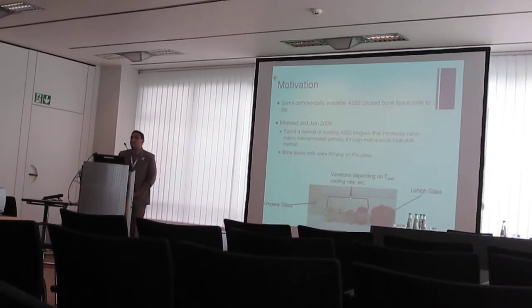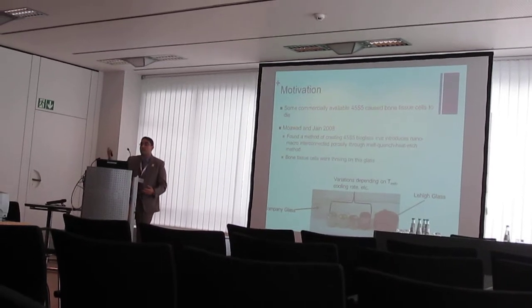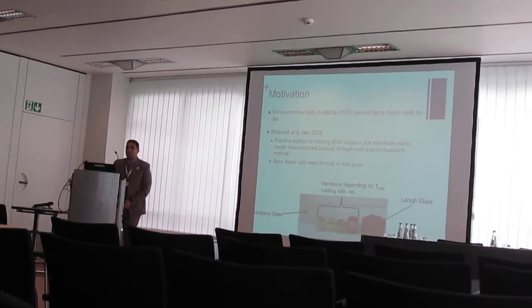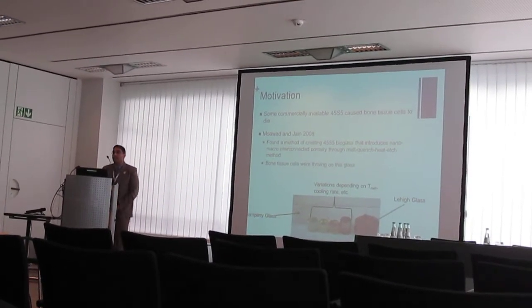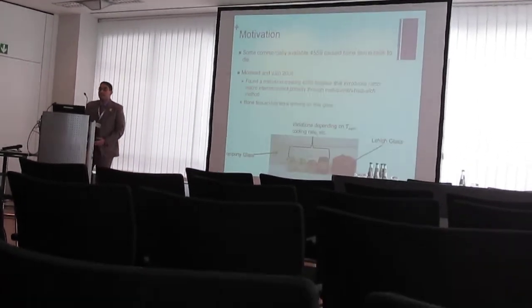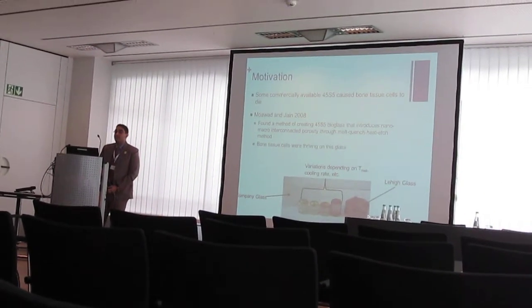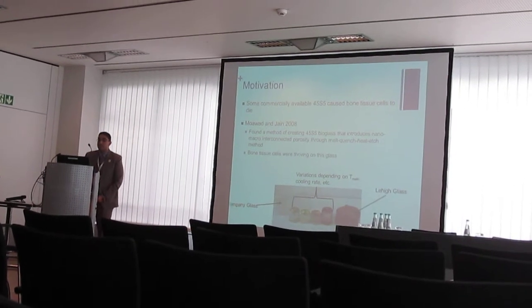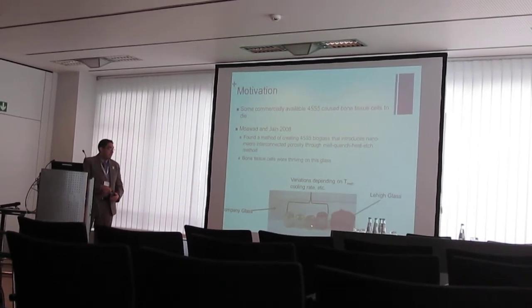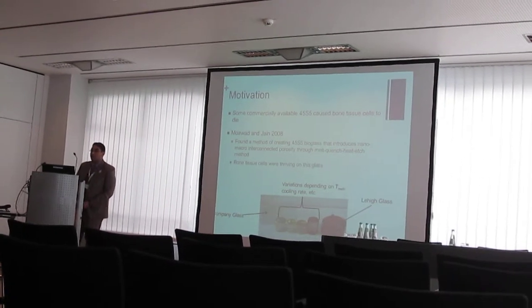We were very interested in seeing what caused this, and we tried to vary the different parameters in the melt quench technique. We determined that if we vary the melting temperature, the cooling rate, and heating rate, etc., we were able to make glass that was more transparent, much like the Corning glass.